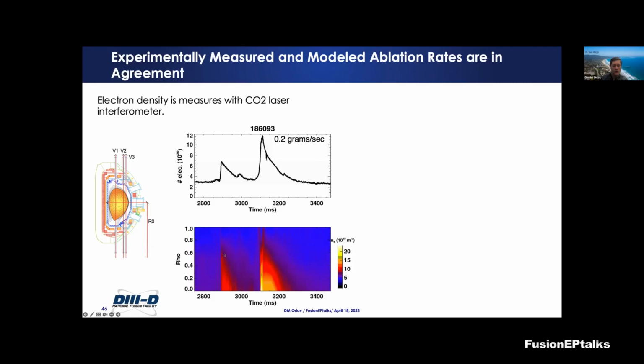In one of the discharges, two pellets went into the plasma, and you can see the density going up here. We could convert that into the number of electrons, and assuming these electrons come from the fully ablated carbon, we could estimate how much carbon was deposited. At the peak, that gave us about 0.2 grams per second of carbon deposited into the core of the DIII-D plasma.